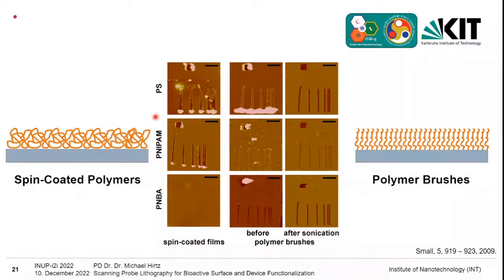polymers. So here are 3 different polymers, and you can always see that the spin-coated polymer will have a widening of line, because when you scratch through it, you can imagine that you drag along these entangled polymer chains. And so by this, you drag along more and more material and you widen the material, while the polymer brushes, as they are more neatly constructed and more stable to the surface, really only scratch around a little bit, and you have your fine confinement or your high fidelity in the pattern later on.